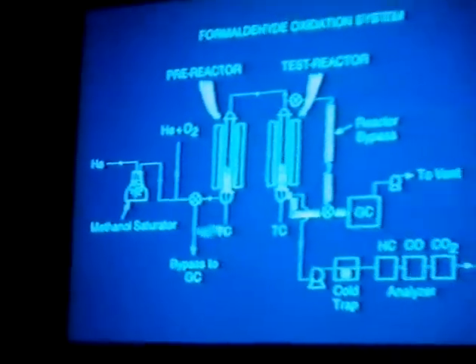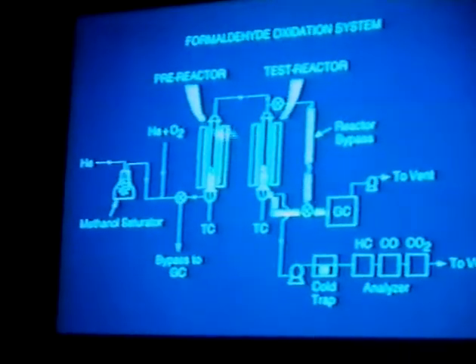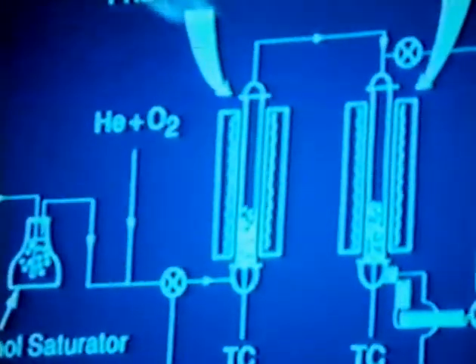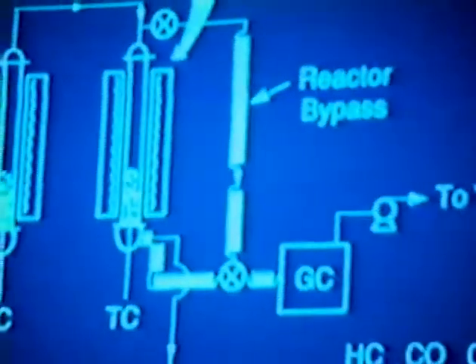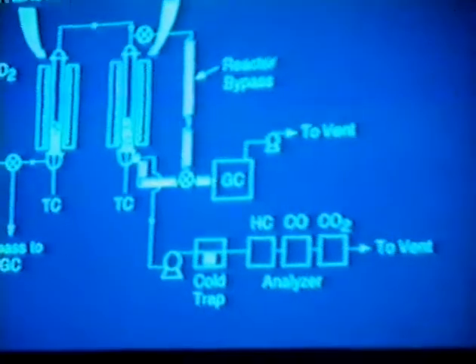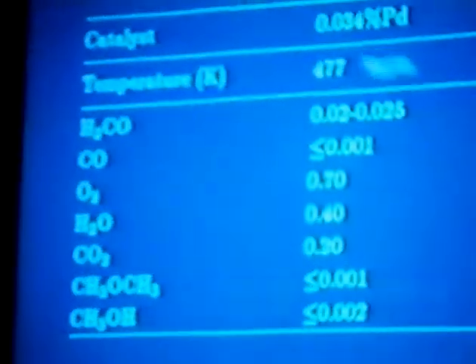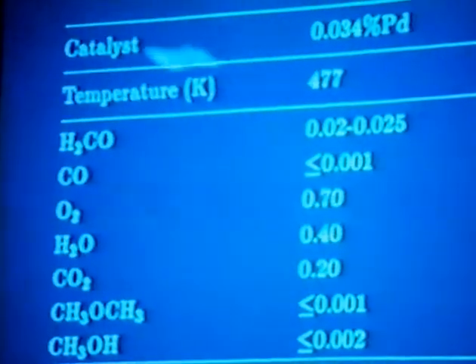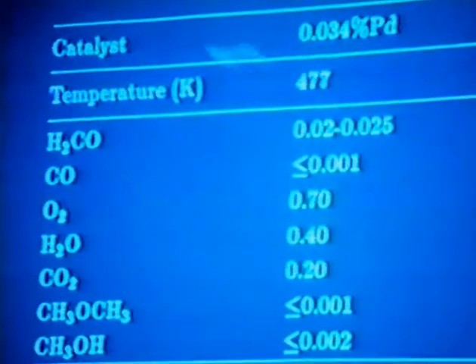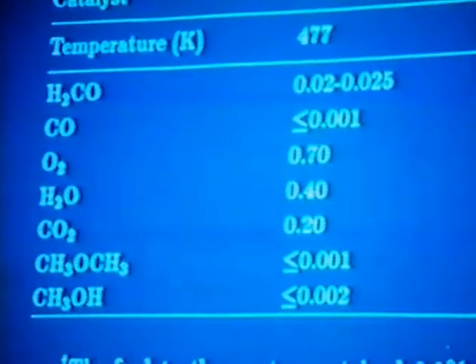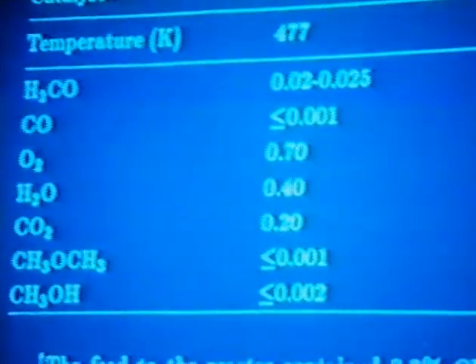Helium is fed through a methanol saturator, then we add oxygen. It goes up in upflow fashion through a pre-reactor, and then the product stream from that reactor is fed directly into our test reactor. Products from that are analyzed in normal analysis train. This table shows the composition of the pre-reactor product stream. And at various times in the study, we used two different catalysts, one being palladium, the other vanadium, again, both supported on gamma alumina.